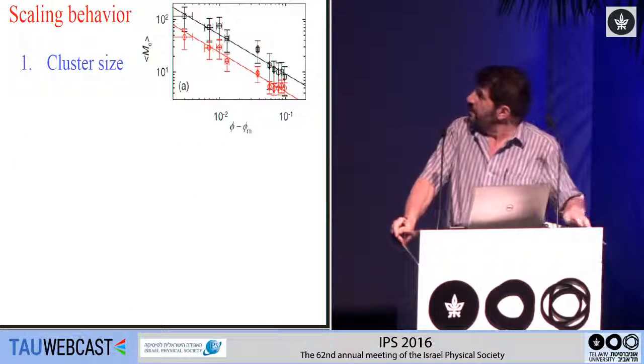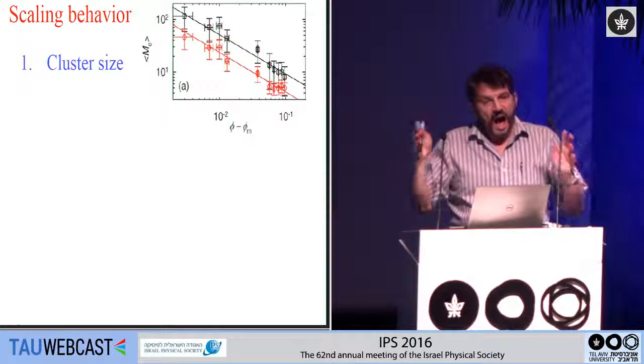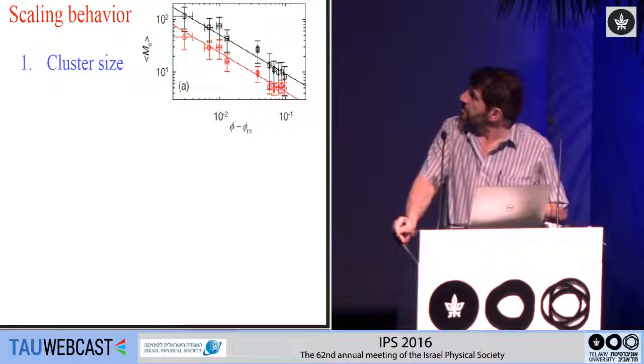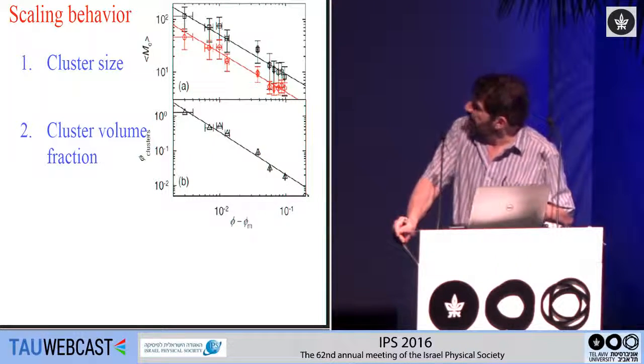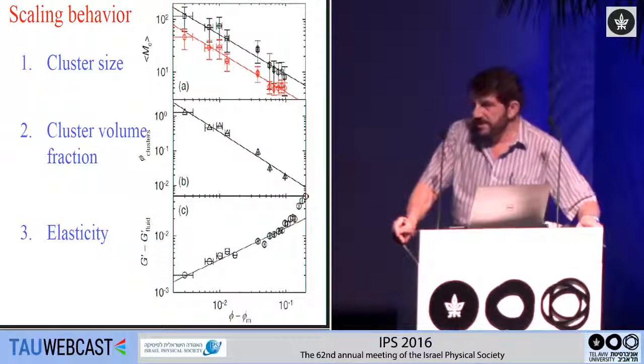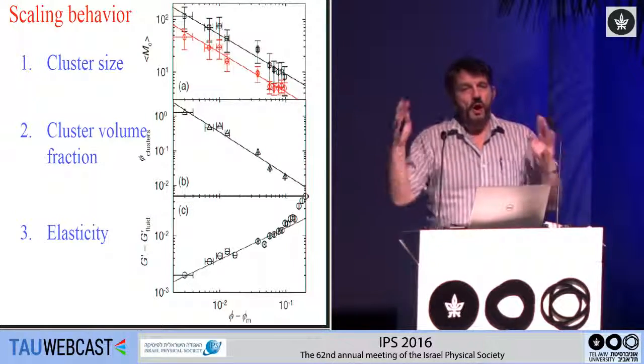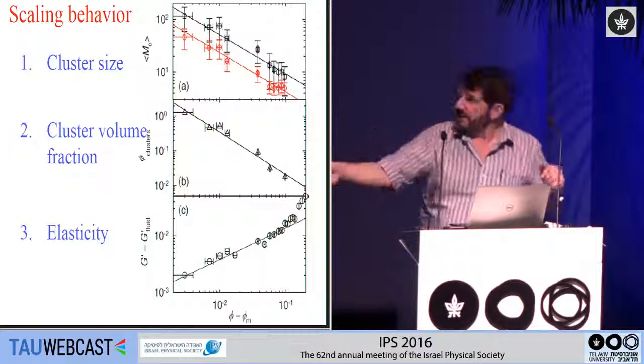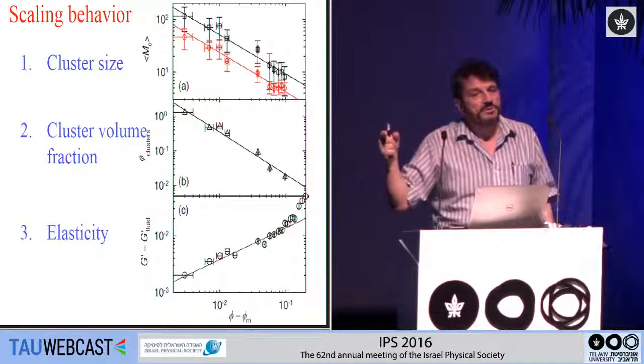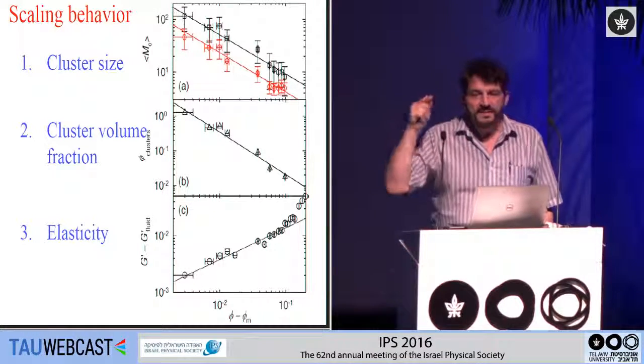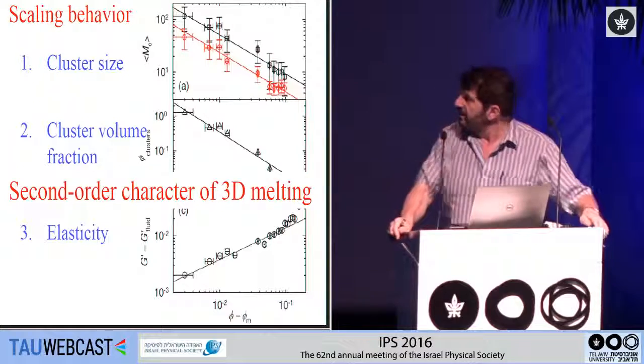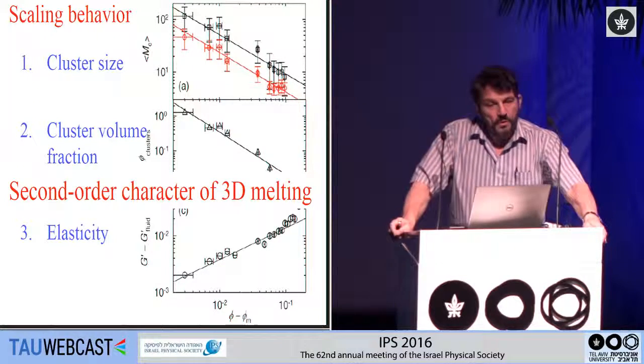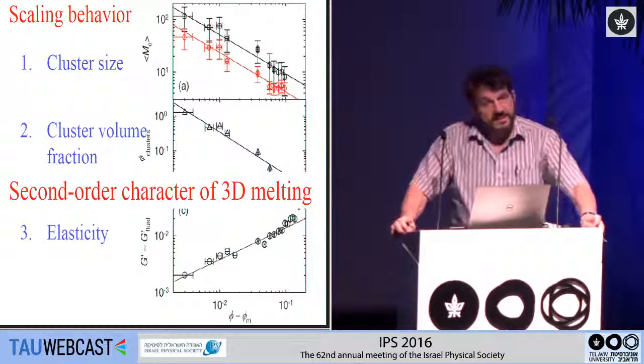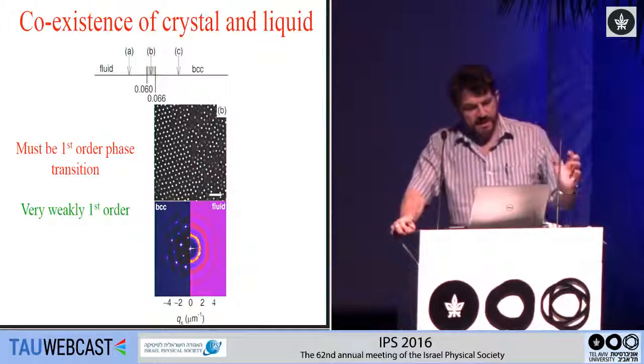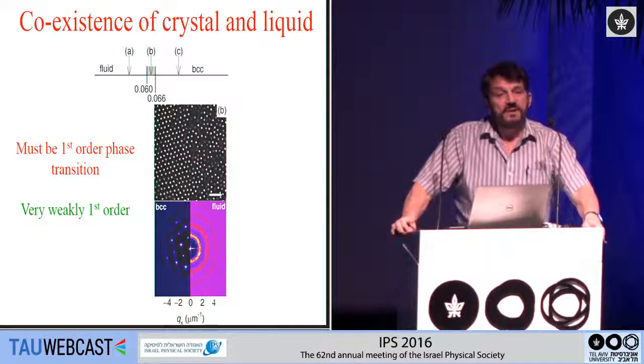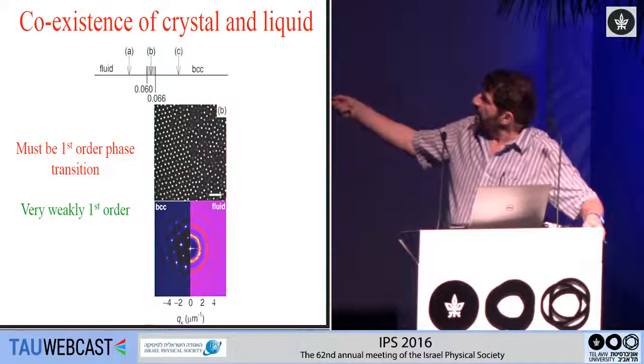So look what I'm showing you. You have a scaling behavior, that is a critical-like behavior, of the cluster size distribution, of the cluster volume fraction, and of the elasticity. So what this says is that even though you are not near melting, you can be away from melting, you can be at any point, and you know how close you are to melting. You know how you're approaching melting. This is exactly the type of behavior that you would get if you had a second order or critical-like behavior. But this is 3D melting. And this is not a critical behavior because there's clearly a coexistence between a liquid and a solid phase.